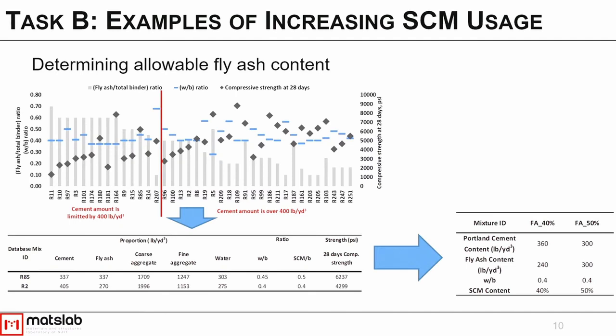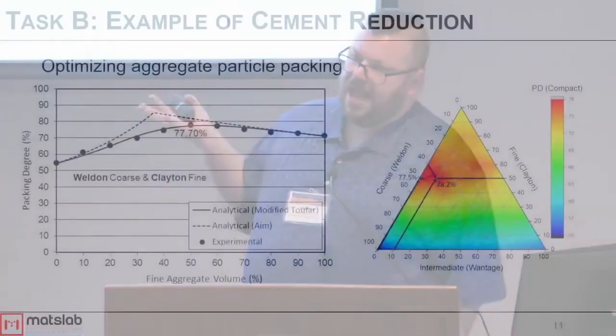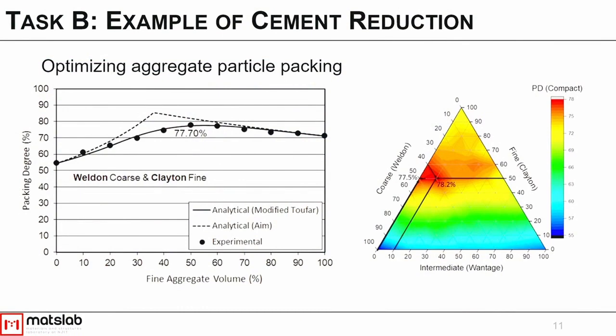From that, we chose some example mixtures that we wanted to keep as our target, and then using our own materials at home, we developed some new mixtures to push that boundary. When it comes to the work with trying to reduce cement, the total cementitious materials content, we focused on optimizing aggregate gradations through particle packing.